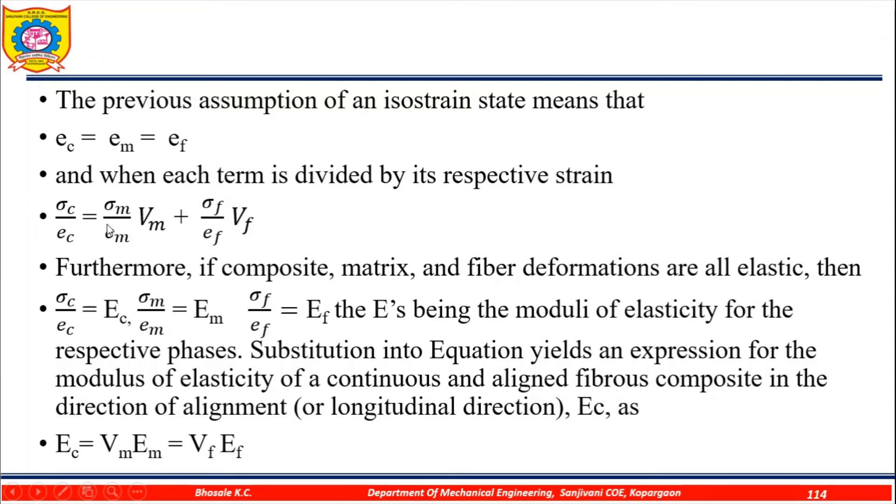Furthermore, if composite, matrix, and fibers deformations are all elastic then sigma/epsilon equals E, the modulus of elasticity for the respective phases. Substitution into equation yields an expression for the modulus of elasticity of continuous and aligned fibers composite in the direction of alignment, the longitudinal direction. E_c equals V_m times E_m plus V_f times E_f.